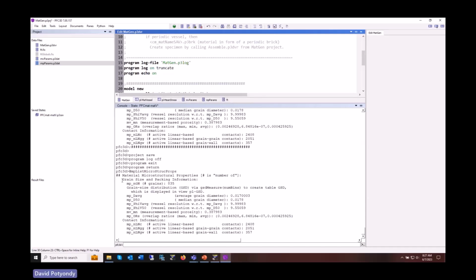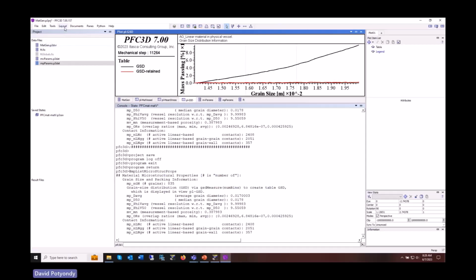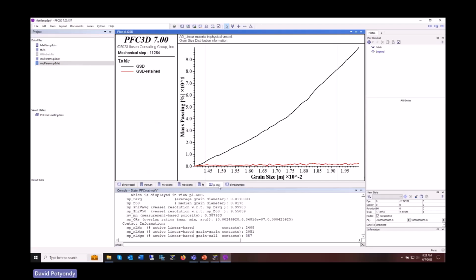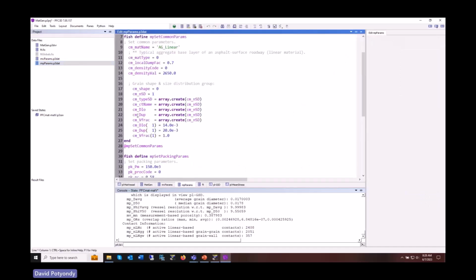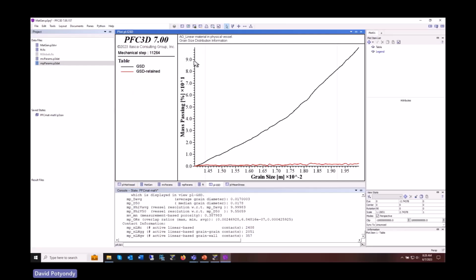MP list microstructural props. So what did the command do? It echoed stuff to the screen: material microstructural properties, so grain size and packing information. Number of grains, 835. You can see the grain size distribution in one of the plots. Document, plot, grain size distribution, layout wide. There. Grain size is going from 14 millimeters to 20 millimeters. That should have been the material property I specified right here: lower diameter, upper diameter, volume fraction of 1, 14 to 20 millimeters. There it is. That's my grain size. This is mass passing from 0 to 100, right?